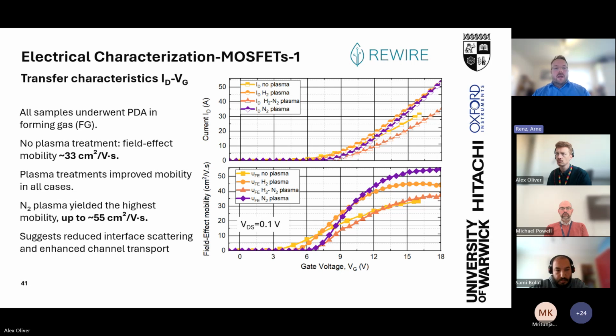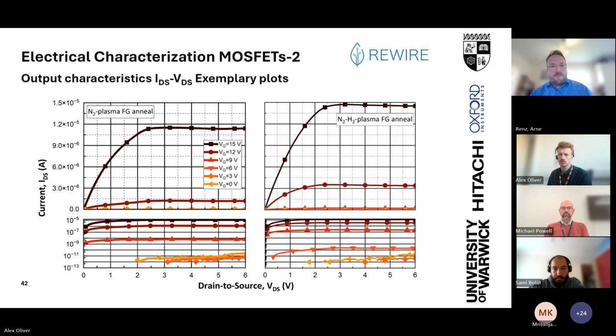It basically means that your field effect mobility is 55 centimeters squared per volt second, which is about 2.5 times higher than what you would normally expect on a thermally grown oxide. And that translates into real device improvements, into real resistance reductions. Next slide, please. And we demonstrated as well that these devices turn on, they behave like normal MOSFETs.